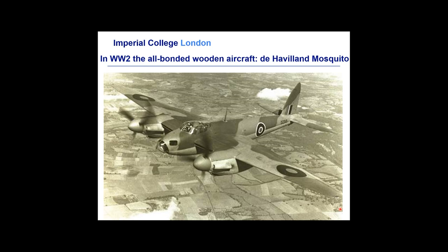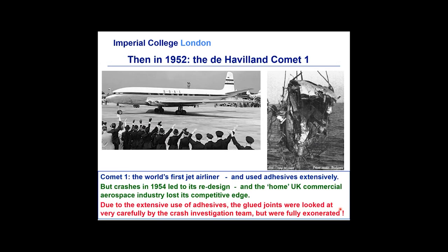Later in World War II, the casein adhesive was replaced by synthetic polymeric adhesive, which was a urea-formaldehyde adhesive, which was far more durable and did not suffer such problems. In the 1940s, the first adhesive was developed for structural bonding of metals. This was a phenolic formaldehyde polymer toughened by polyvinyl formal. The first jetliner, the de Havilland Comet 1, flying in the early 1950s, needed to keep the weight down. And so this adhesive was extensively used to bond the thin aluminium alloy panels.